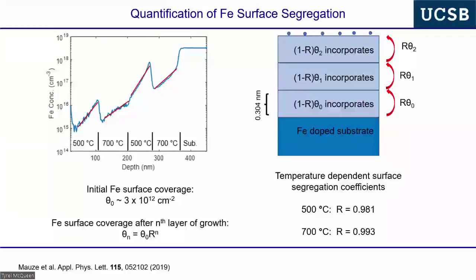And so if you fit this to models of the iron coverage on the surface, it turns out that we have an initial iron concentration in these measurements of about 3 times 10 to the 12. Now, if you take this 6 to 8 times 10 to the 22 atoms per cubic centimeter and take that to the 2/3 power, you're going to find that on a surface, you have about 10 to the 15th sites per square centimeter, for anything. It's always on the order of 1 to 2 times 10 to the 15th. So this initial coverage is less than 1%, 0.3% or less. And most of this is riding on the surface because the incorporation coefficient, this is the riding coefficient, is 99.3%, meaning per monolayer only 0.7% is incorporating.